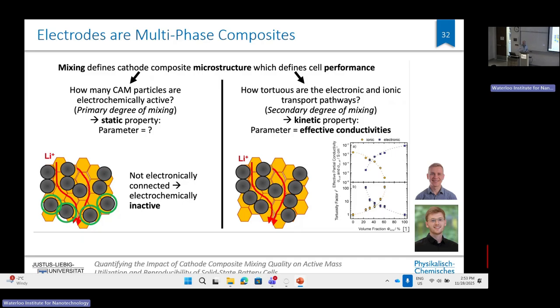You prepare your cathode, you measure it in a cell, then you get a certain, let's say, capacity as a function of rate. And you think, okay, if this is not good, my material is not good, or, well, I did not prepare my composite properly, whatever. But in practice, I think what is important to understand is that there are two different effects that should be separated before you misinterpret your results. One is simply wrong mixing: you can have particles that are simply not connected. Let's assume that they are all connected to the solid electrolyte, the yellow background. But it may be that these four particles here are not electronically connected. They are isolated electronically, so they cannot be charged. You need to contact them fully, ionic and electronic. And this has to be determined.